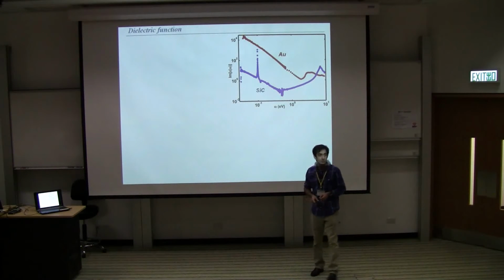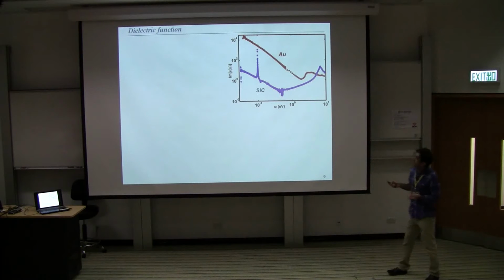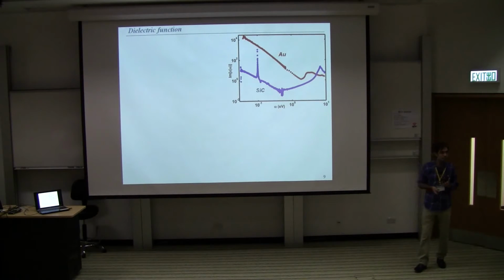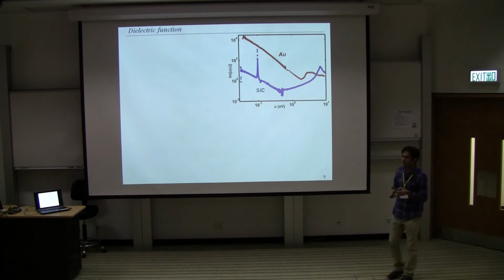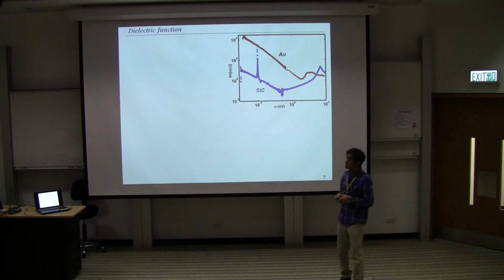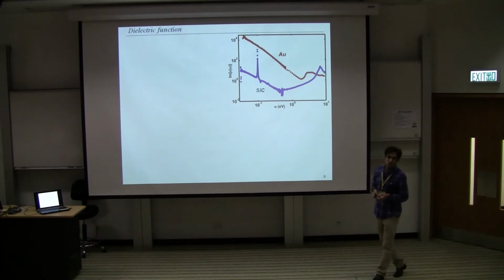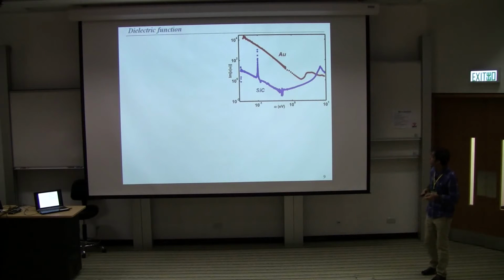Measurement of the Casimir force for silicon carbide, as for any other dielectric material, is complicated by the trapping of electrical charges. The problem can be significantly reduced by doping the material, which makes it slightly conductive.